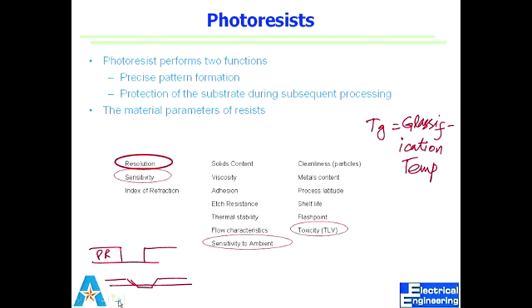Etch resistance, again, goes back to how much of it gets etched given one recipe. Thermal stability, flow, it's all interconnected. Ambient shelf life translates into how long we can keep it, right? If I buy a resist for $2,000 and it's good for 2 months, I may not be able to use the whole gallon, because all we use in one exposure is one squeeze of a pipette, which is 2 ml at the max. Using 2 milliliters of a gallon is going to take months before I finish it. So if it expires in 2 months, I lose that. From an industry point of view, these are some of the important things.